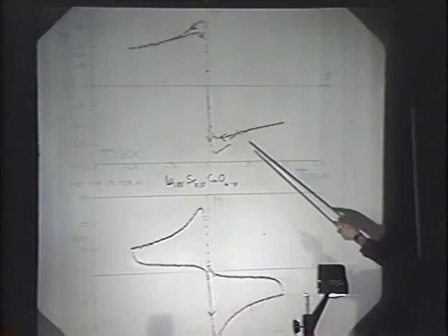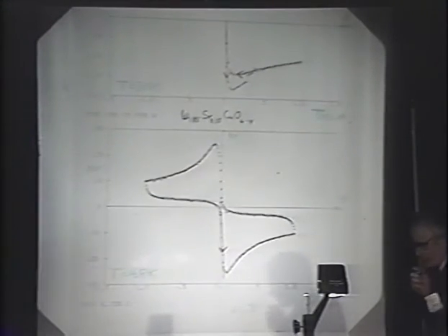Now, at 30 degrees Kelvin, the hysteresis loop looks almost totally reversible. There may be a small irreversibility here, and this indicates that pinning effects and thus critical current in the field are very small. However, the situation becomes a little better as one goes down to lower temperatures, in particular at about 5 Kelvin. The hysteresis loop opens up, and this means there are more optimistic possibilities of having enough pinning to be able to use this material in practical applications.